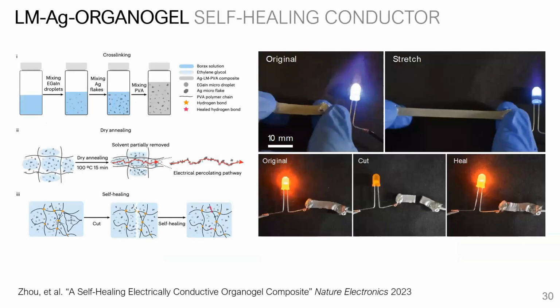In the pristine state, you have this very stretchable circuit. Again, we don't have to do any mechanical sintering on account of the presence of the silver flakes. And then because of the liquid metal, when we cut these materials and bring them back together, they spontaneously fuse. The PVA and borax form the hydrogen bonds that are needed to restore the mechanical integrity, and then you have the liquid metal to help restore the electrical connectivity.